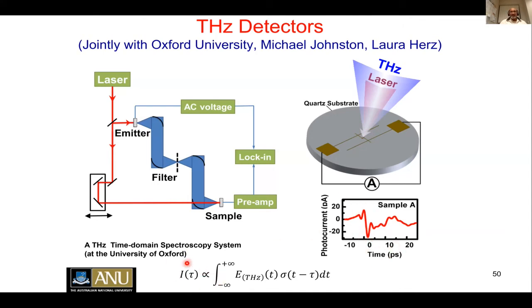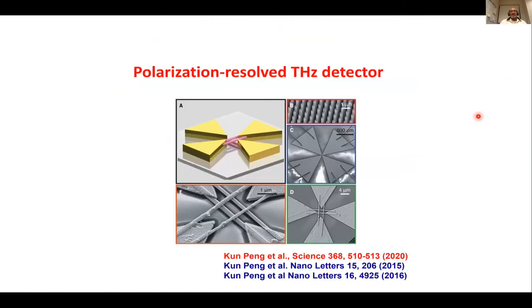And if you measure the current as a function of time, you can measure the electric field of the terahertz pulse and the conductivity of the material as well. So that really helps to extract the full electric field of the terahertz pulse by using this particular technique. So Kun Peng has fabricated all the devices at the ANU, has gone to Oxford University and did the measurements. And then we were able to demonstrate a wide variety of gallium arsenide-based nanowire terahertz detectors and indium phosphide-based nanowire terahertz detectors.